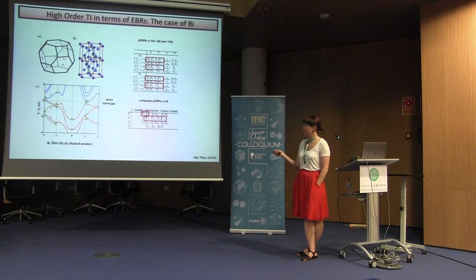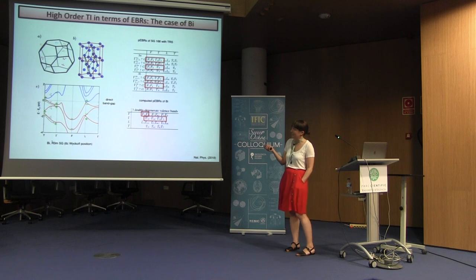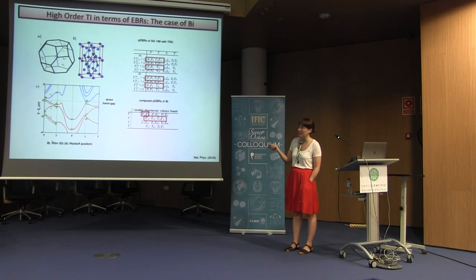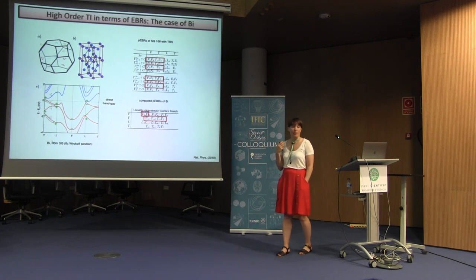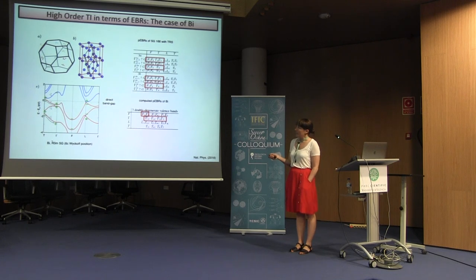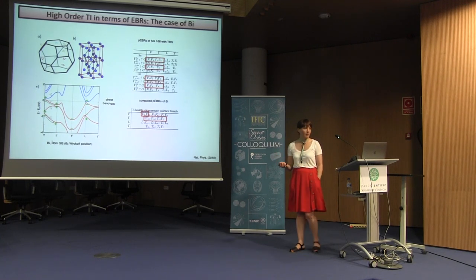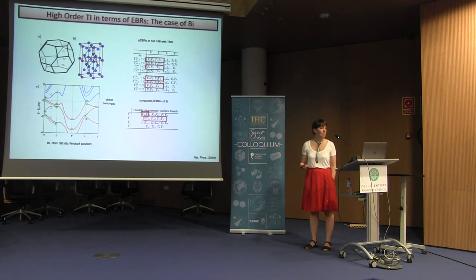So we decided to calculate theoretically the irreps at the high symmetry points and see whether they form an elementary band representation, which is here. I find it difficult to see, but I can tell you that the occurrences are not random. I mean, you have a gamma here, we need to have a gamma here, and we need to fulfill all the irreps at high symmetry points to have a trivial trace. And then we did the calculation for the particular case of bismuth, and what we see below the Fermi level is that actually this comes from a split EBR. So bismuth is actually topological.